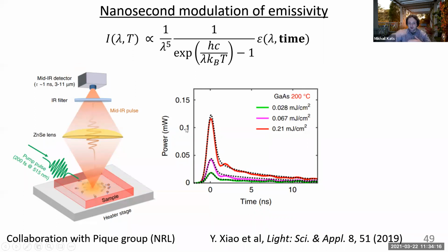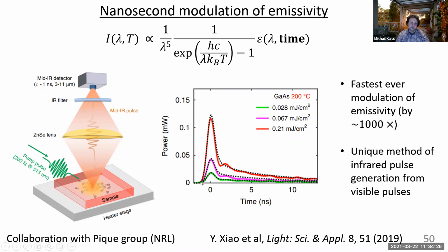And then the carriers recombine, and the emissivity goes back down again, and then your thermal emission power goes back down again. And so essentially, we're able to observe this emissivity modulation on a time scale of about a nanosecond or a couple of nanoseconds. And to our knowledge, this is actually the fastest ever modulation of thermal emissivity by something like a factor of 1,000. And so also, this is an interesting and unique way of generating infrared pulses from visible pulses.